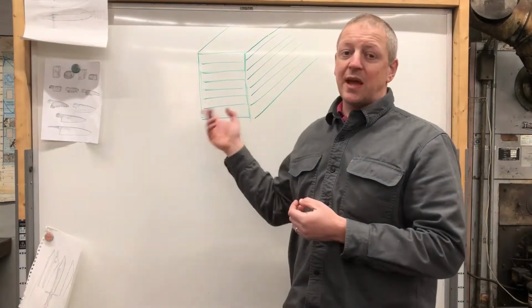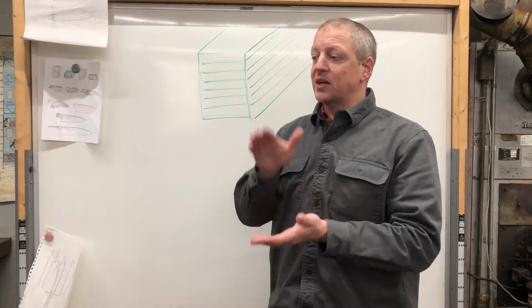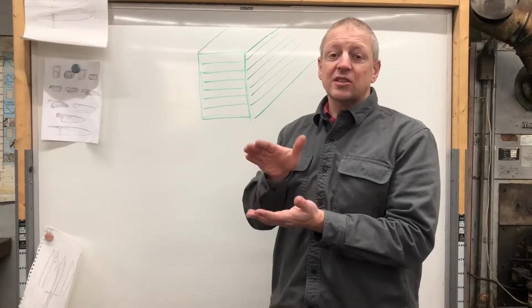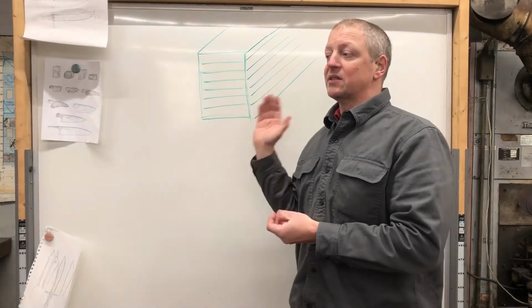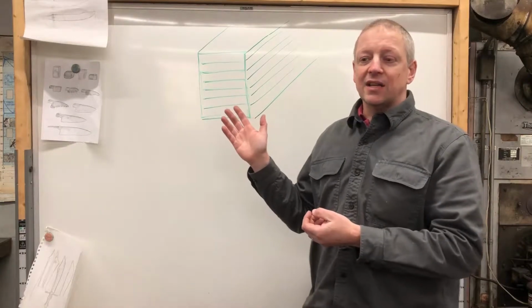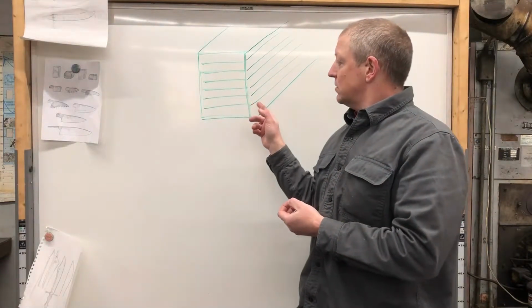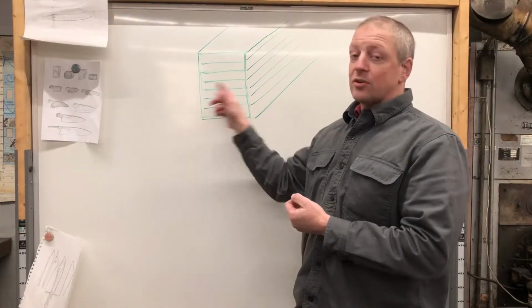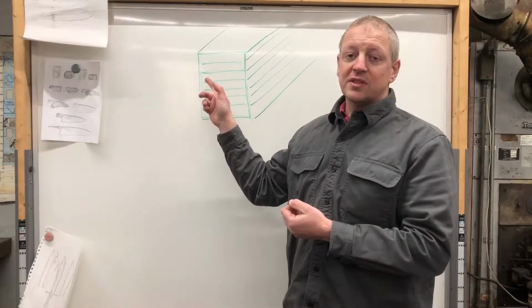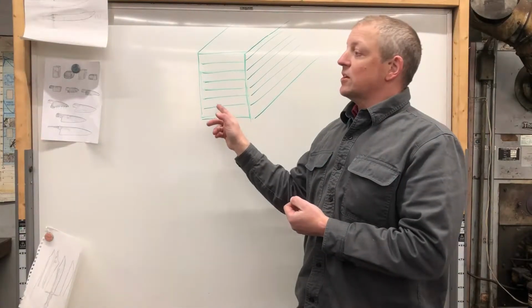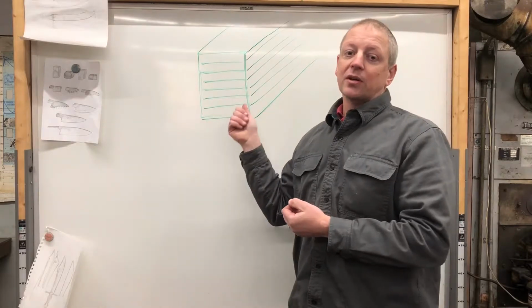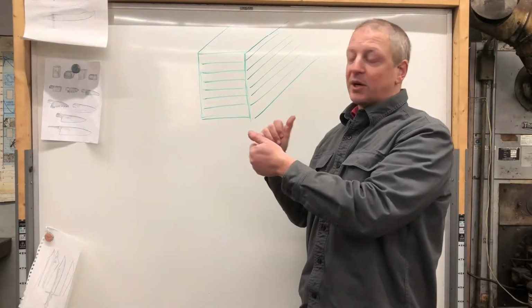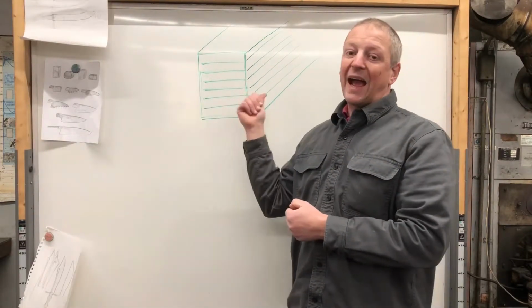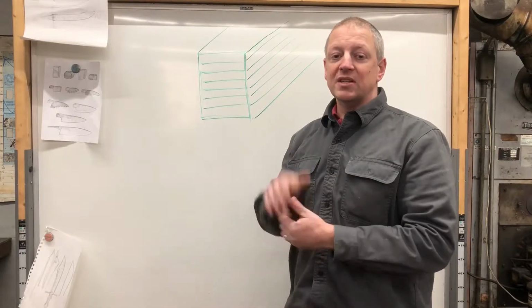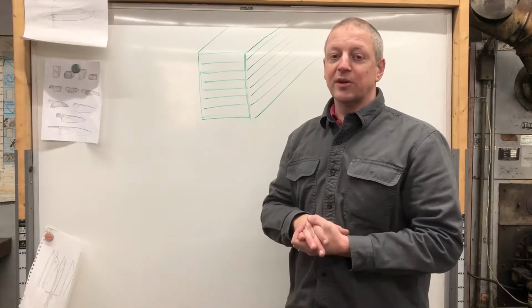This really helps the chemistry work, just because it makes sure that there's nice close contact between the steel and any oxides you have. And also, the tighter these layers are together at this stage, the easier it is to develop that positive pressure of carbon monoxide or carbon dioxide pushing out and maintaining that positive pressure between the layers.